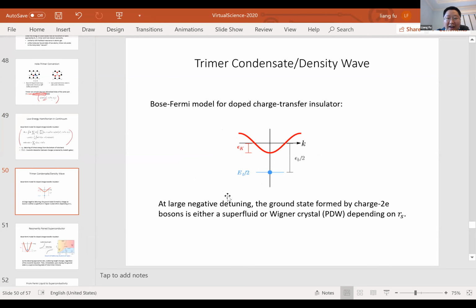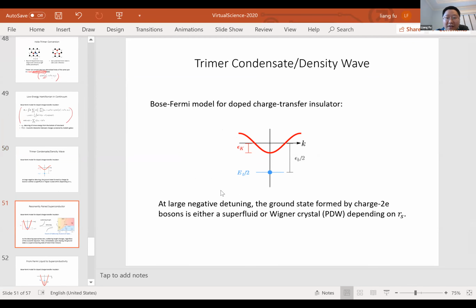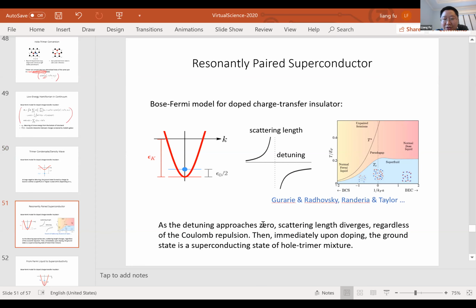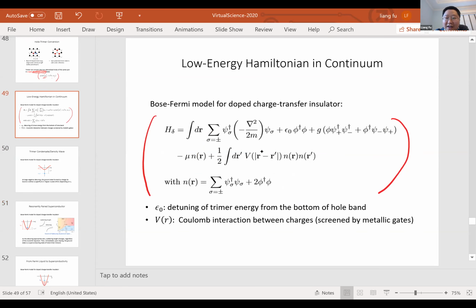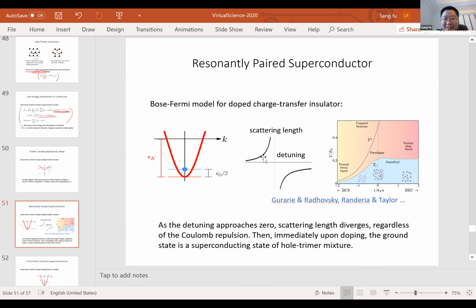And again, this is just stating the same thing, that when the detuning is negative and large, when the trimers are the lowest energy excitation, the ground state is just charge 2e bosons, which is either a superfluid or a Wigner crystal. But as they are brought to resonance, when the detuning approaches zero, the scattering length diverges. In this case, the resonance process, the conversion between the trimers and holes, always dominates over the Coulomb repulsion. This is the key of resonance physics. Near the resonance, the scattering length diverges, and this physics is universally described by the BEC-BCS crossover, just like in the cold atom gas.